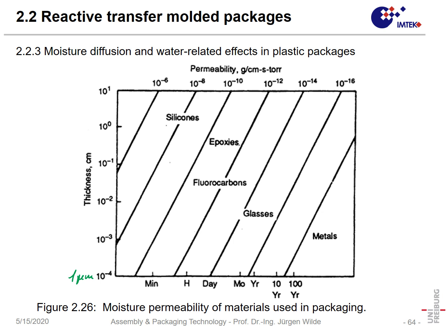According to that model, it takes between 10 and 100 years until the moisture permeates the metal. If on the other side we have something like 1 millimeter here, then we could say, it's 10, 100, it's 10,000 years or so until the water permeates 1 millimeter of such a tight metal. So that is something which is very important.